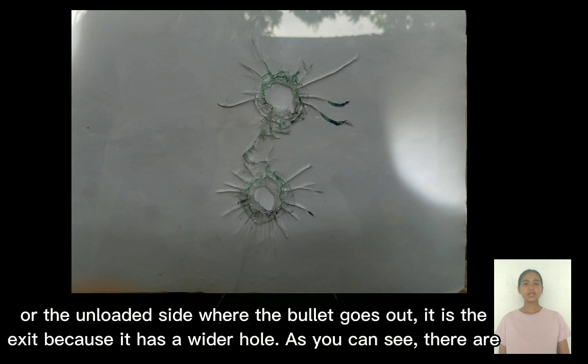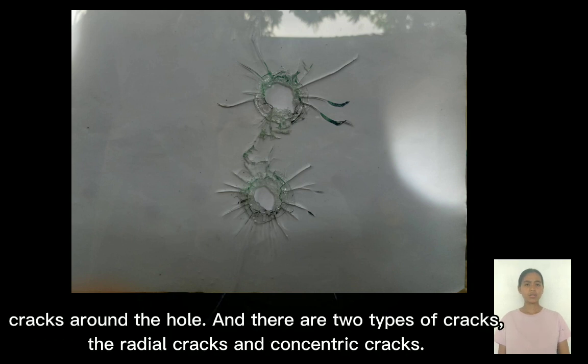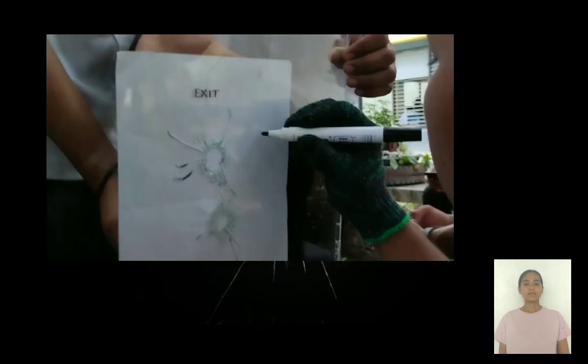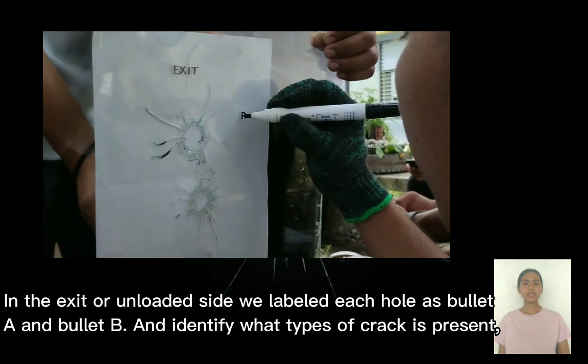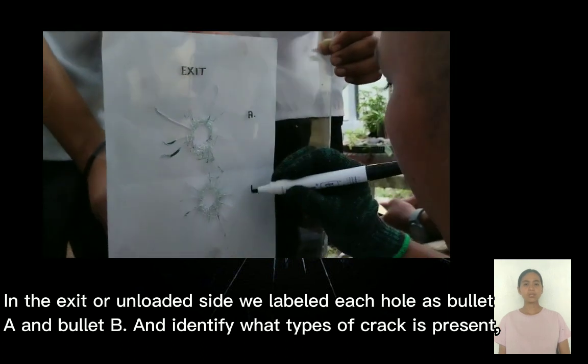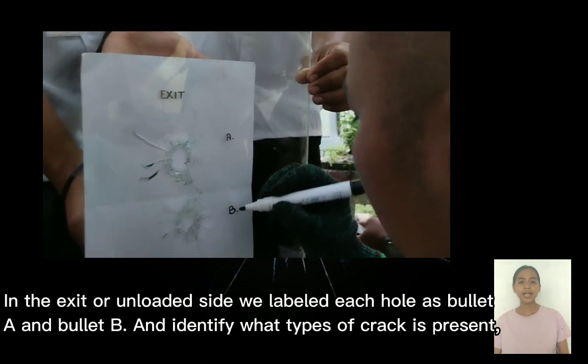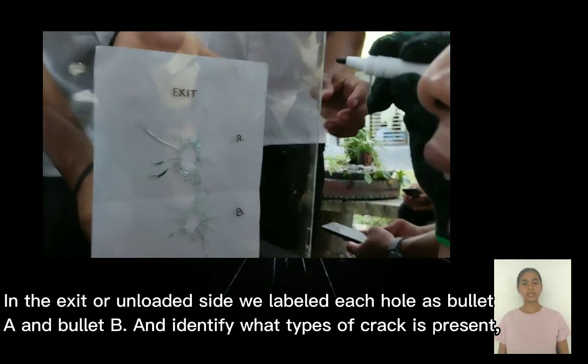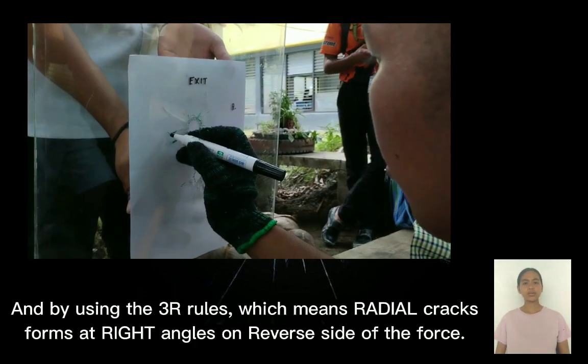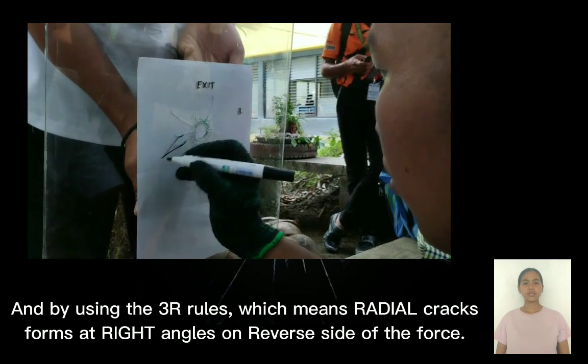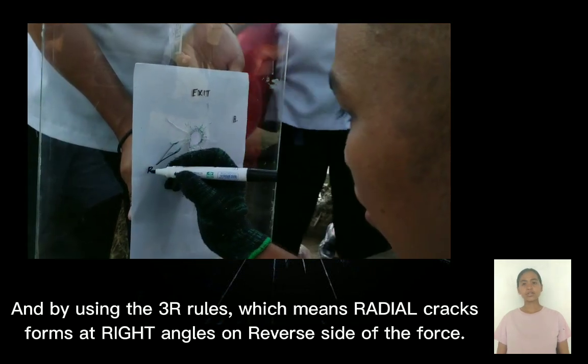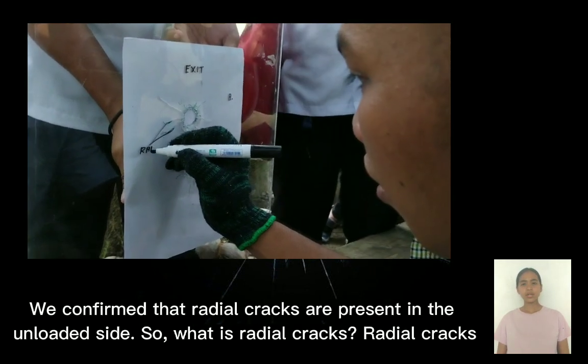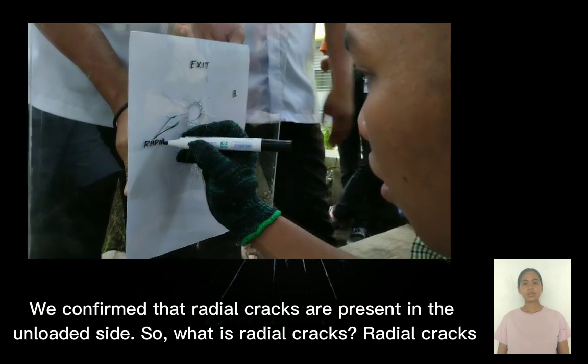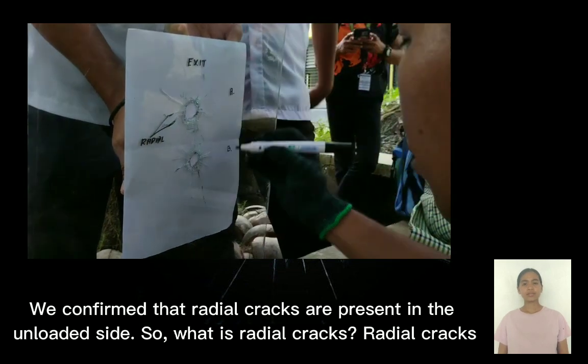As you can see, there are cracks around the hole, and there are two types of cracks, the radial cracks and the concentric cracks. On the exit or unloaded side, we labeled each hole as bullet A and bullet B, and identified what types of crack are present. By using the 3R rule, which means radial cracks form right angles on the reverse side of the force, we confirm that radial cracks are present on the unloaded side.